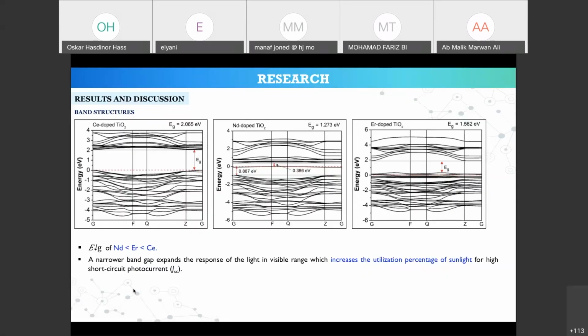And of course, after you dope, the electronic properties also change. We can see the band structure differs with a different dopant, and also we can see the gap. Okay, here we have two terms. First, electronic structure. The second term is electronic band gap. They are different actually. The structure, we can see the structure, and then the gap just focuses on the gap between the valence and conduction band.